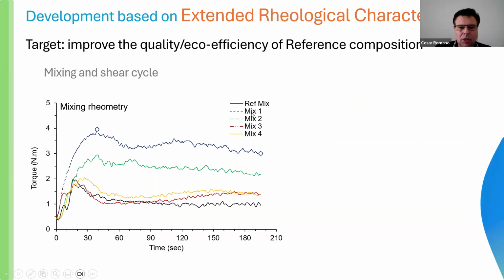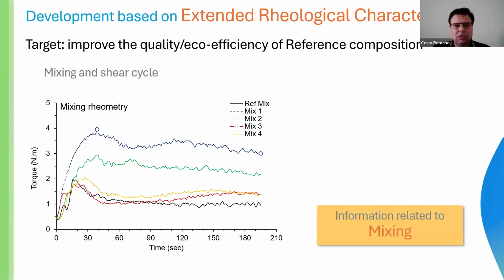And we had here, for these 1 and 2 mixes, we had problems with the energy of mixing. So there are in some places, the mixing is continuous. And it's a very good strategy to improve the productivity in the field. But using these 2 kinds of composition, maybe it would not be possible to produce in a continuous mode. But here, we had very, very low energy of mixing, and we had considerable differences between these 3 and these 2 about the consistency after the mixing. And we had here, using this first evaluation of our extended rheological characterization, information related to the mixing stage.